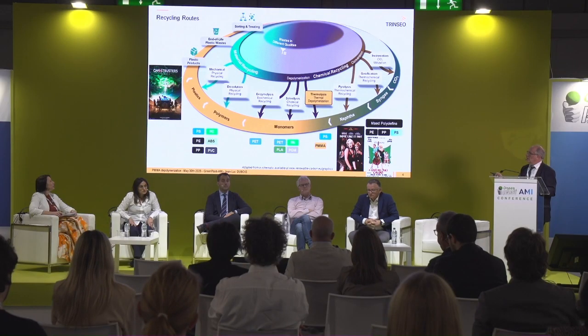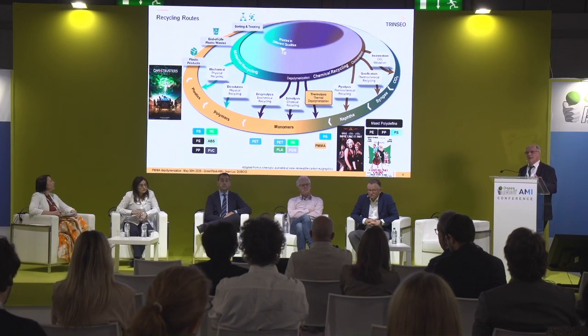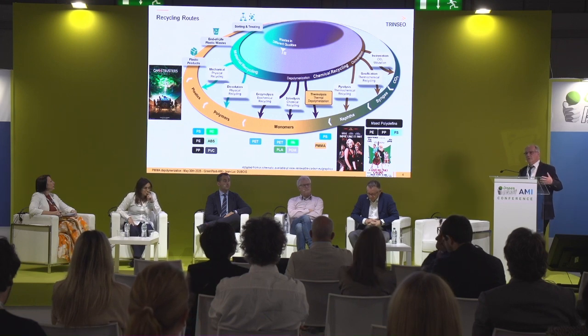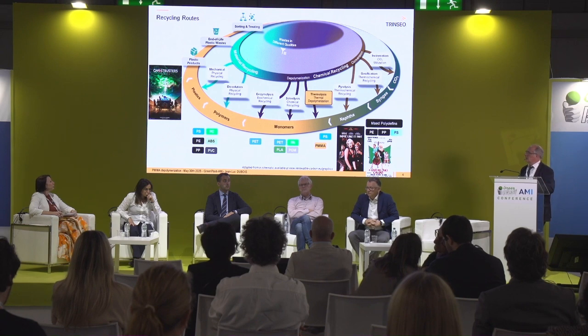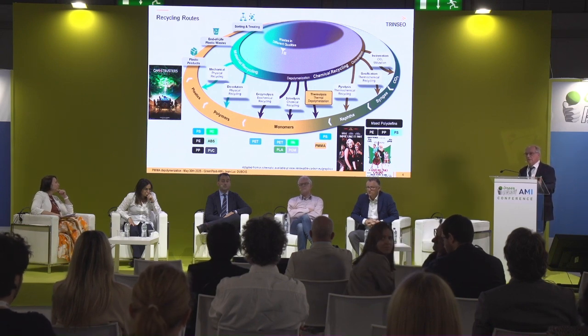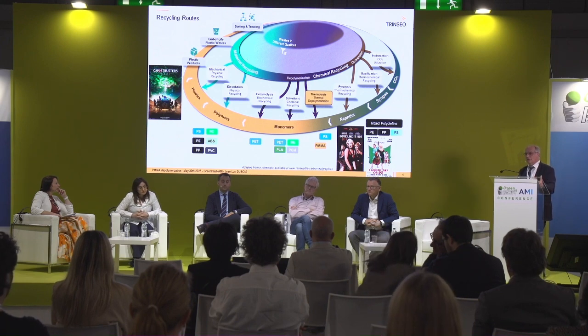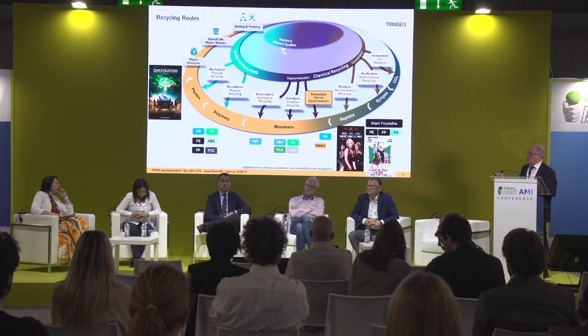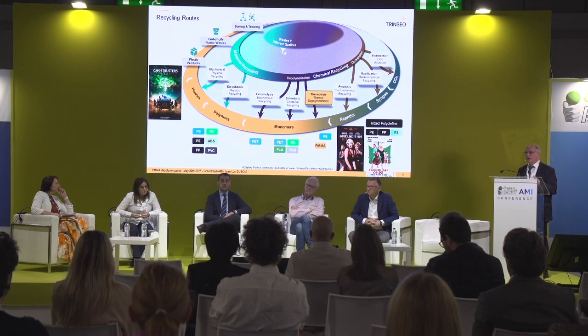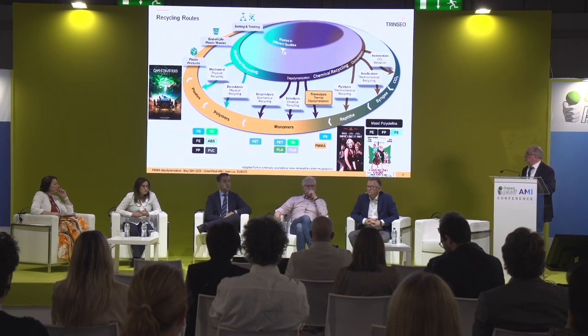What I would stress is, here, I've put this picture, Ghostbusters: Legacy. The challenge that we have in recycling is that there are plenty of additives which have been put in plastics, and some of them are no longer allowed today. So we need a technology, because mechanical recycling cannot do that. It will not be able to remove these additives from the plastic. They will be trapped in the plastic. Selective dissolution with the right material is also able to remove some additives, so in this case it's appropriate. But that's the challenge for the technologies that we develop, to be able to remove additives that are no longer allowed today. That's why depolymerization is quite appropriate.